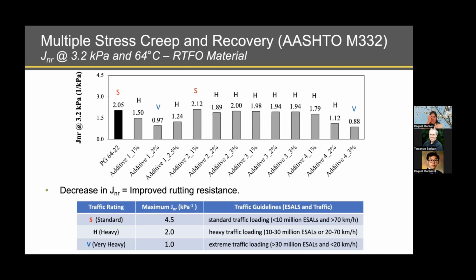One parameter also that is obtained from the MSCR test is the traffic rating, that is indicated by these letters. You can see here that the base binder and additive 2 at 1% result in a traffic rating of standard, which is for traffic of less than 10 million ESALs and speed higher than 70 kilometers per hour. And for additive 1 at 2% and additive 4 at 3%, we got a traffic rating of very heavy, where we can use these binders for traffic that is higher than 30 million ESALs and less than 20 kilometers per hour as traffic speed. And the remaining of the graphene-modified binders were all graded as heavy, being appropriate between 10 and 30 million ESALs or a speed of 20 to 70 kilometers per hour.